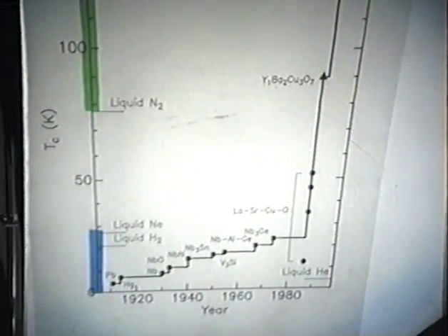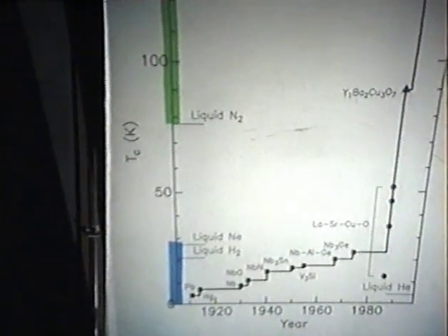And so there the matter rested, at 50 Kelvin, until a guy called Paul Chu in Texas, who's an expert on superconductors. He figured that normally if you take a superconductor and you squeeze it, its critical temperature goes up a bit. So he tried squeezing this material by putting some smaller atoms in, and bingo, he put an yttrium in instead of a lanthanum, and wow, it went up to 90 Kelvin.